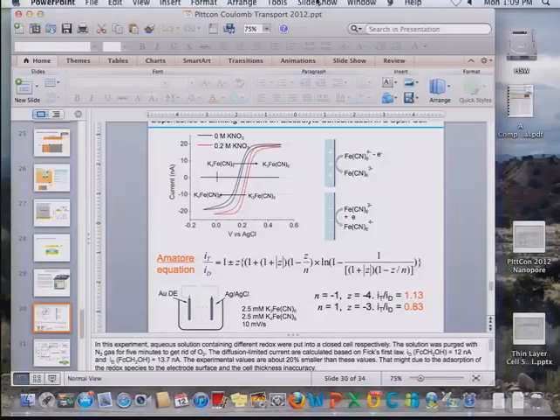And there's a brilliant gentleman in the back of the room, an old French guy, Amatore, Italian-French, you can call him either. A lot of us worked on this problem. Mark Wightman worked on this problem, other people in the room 20 years ago. But the equation that really, in my mind, grabs everything is what I call the Amatore equation, which predicts this decrease or increase in current when you take out the electrolyte. For these two reactions, you expect this current to decrease by about 15%, and this one to increase by about 15%. And you see qualitatively the experiment matches up with the prediction from the Amatore equation.